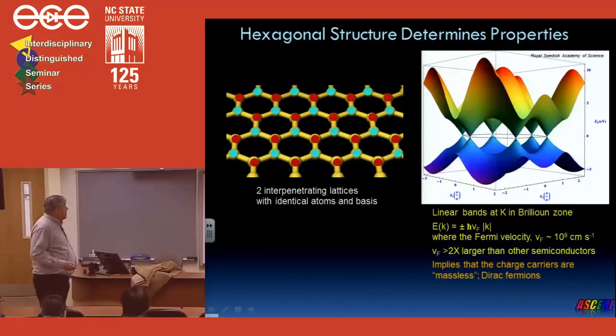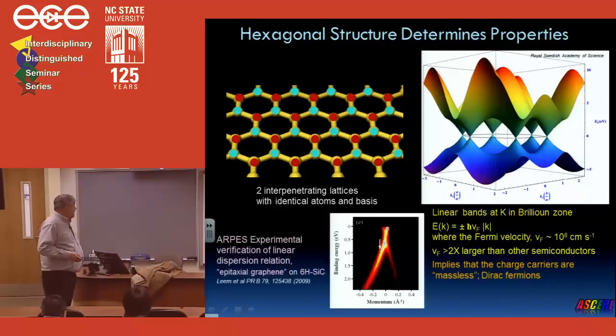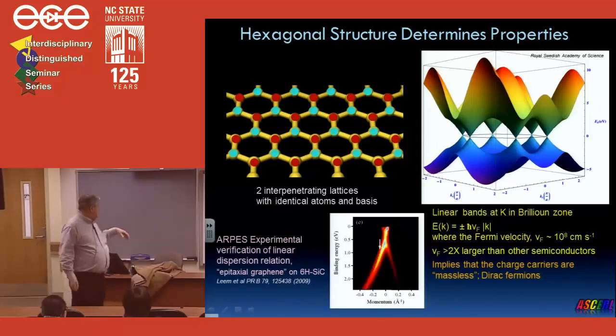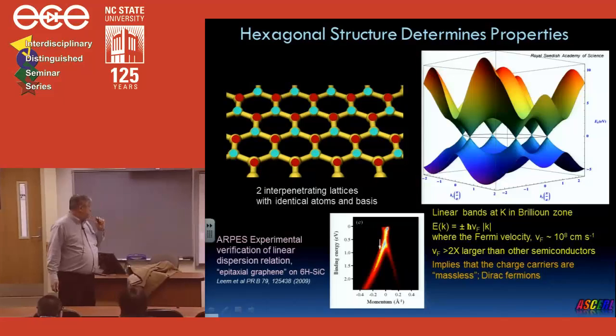In addition, you can have electrons as carriers or holes as carriers, and it's ambipolar. So there's no band gap between them, so you can switch an electron to a hole with very little energy loss. And this was verified experimentally many times. This is an example of the verification using angle-resolved photoelectron spectroscopy, also called ARPES. And you can see the linear bands in the valence band in this particular figure.